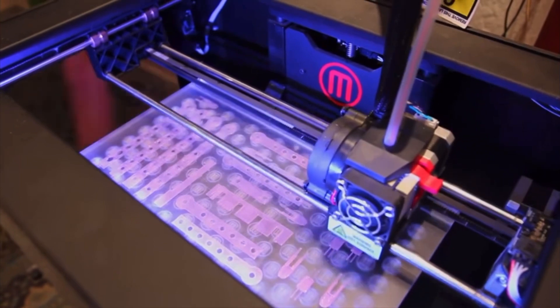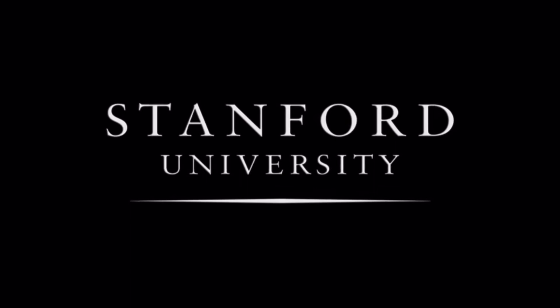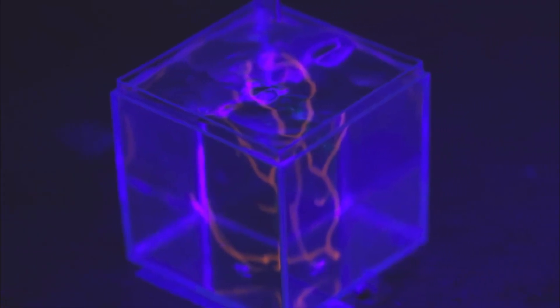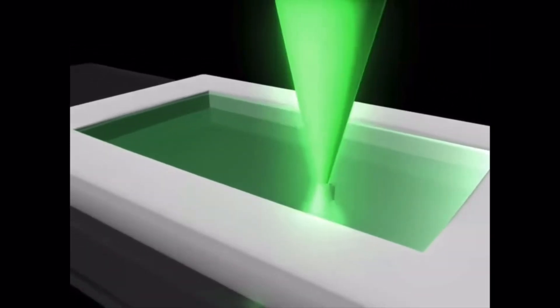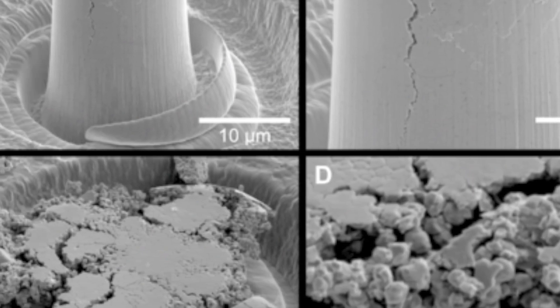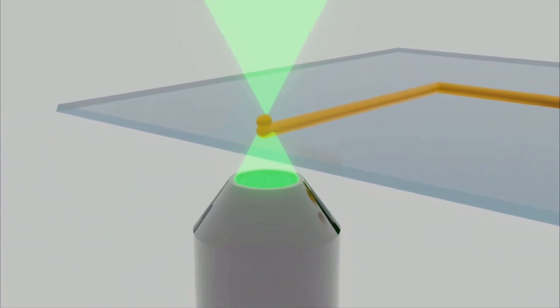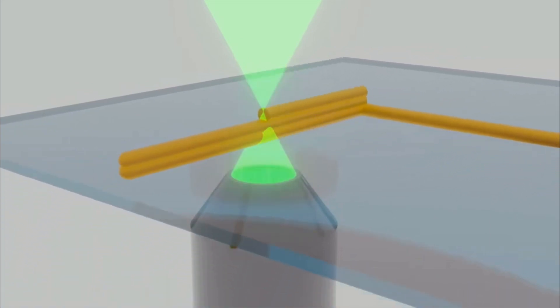Nanoscale 3D printing is also unlocking new printing materials. Researchers at Stanford University fused metal nanoclusters with resin-like mixture to create a stronger, lighter-weight material. Using two-photon lithography, they discovered that their nanoclusters actually accelerated the chemical reaction needed to print, which produced a substance that was a mixture of the metal and specialized resin. With this accelerated reaction time, they can print at a speed of 100 millimeters per second, which is roughly 100 times faster than what had previously been possible.